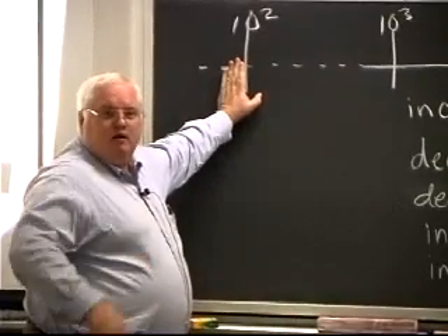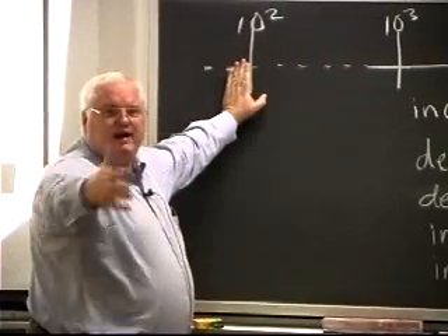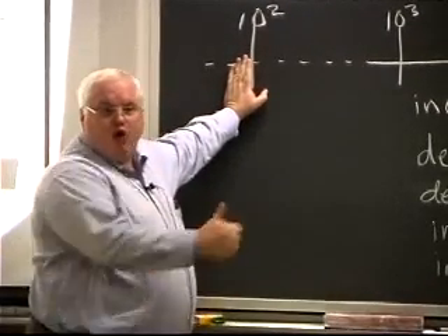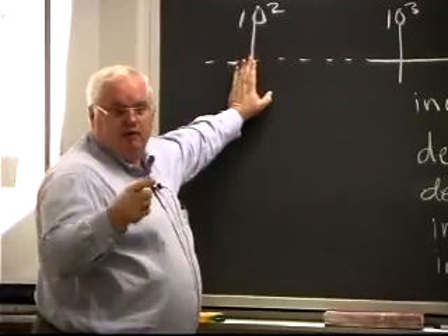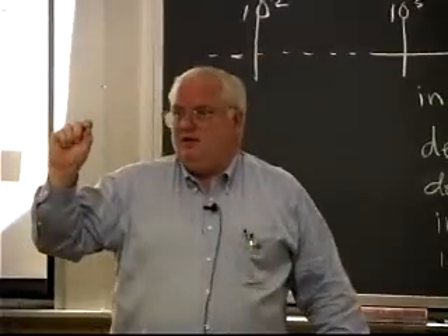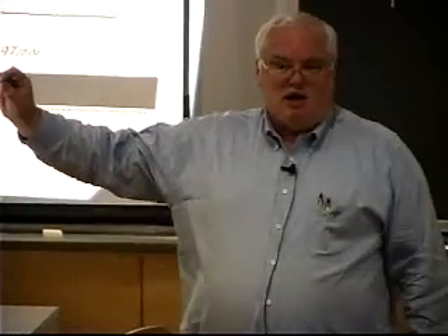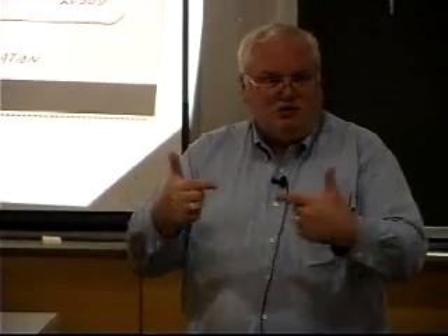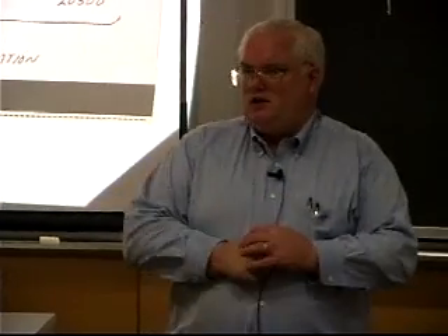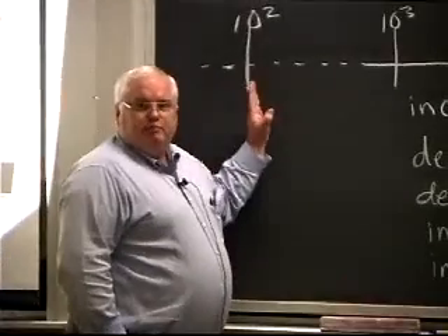In any case, the point is, at 100 watts per square centimeter input, you end up getting to the point where when things start getting red enough, they start radiating the heat away or conducting it down the thing, although that one's so thin that the heat conduction loss out the ends is a relatively small fraction compared to the center. I was getting a reasonably wide heat zone compared to its length. So it's not really conduction, it's really radiation, but most metals melt at a high enough temperature.